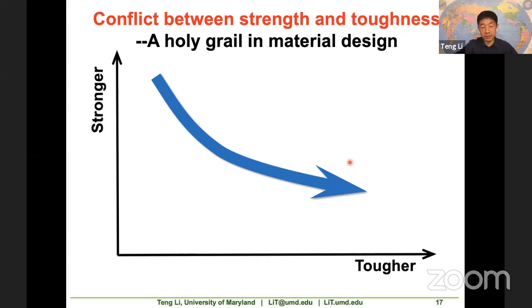Generally speaking, if you have a stronger material, it tends to be more brittle. Now, if you have a tougher material, typically this material is not that strong. I typically use diamond as an example. Imagine you have a big chunk of diamond. It's arguably one of the strongest materials out there. You better keep it that way. Don't drop it on the floor, because if you drop it on the floor, it breaks into pieces and your value decreases significantly. That's because this very, very strong diamond is very, very brittle.